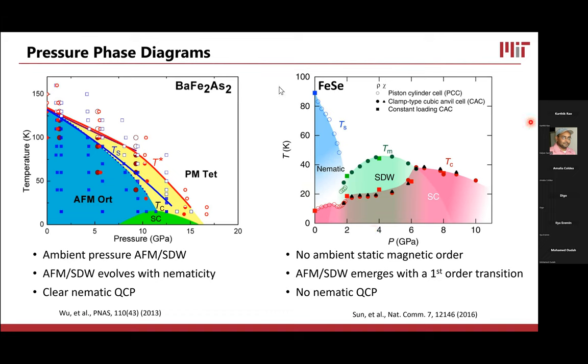So that's the first key indicator that there might be something else going on with nematicity in iron selenide. Then we can look at how the phase evolves under pressure. And what we find is this picture here, where a magnetic order does eventually show up at large pressure, but it doesn't seem to be tightly coupled to this original nematic phase here. As we go up in pressure, the nematic transition suppresses in temperature, and all of a sudden we get a first order transition over into a spin density wave that also has the same kind of structural and magnetic order as the iron pnictide spin density wave. But you can see that it's first order.